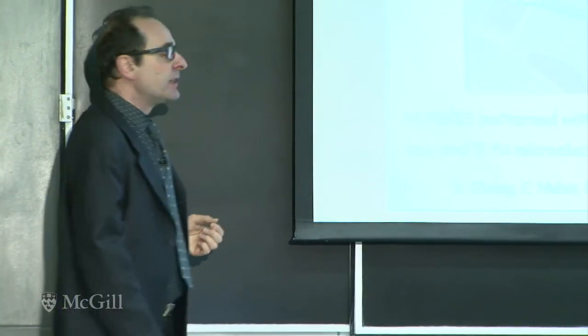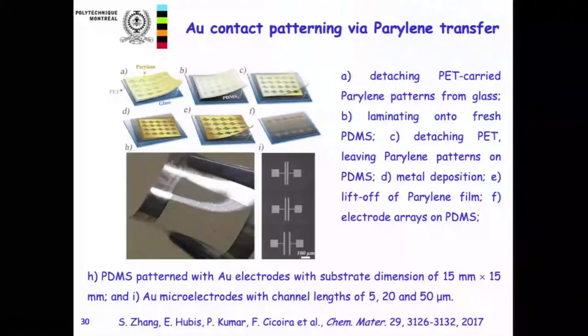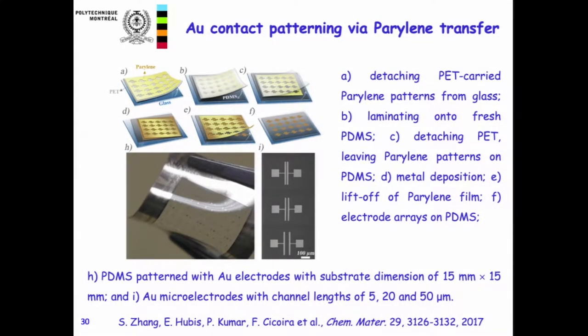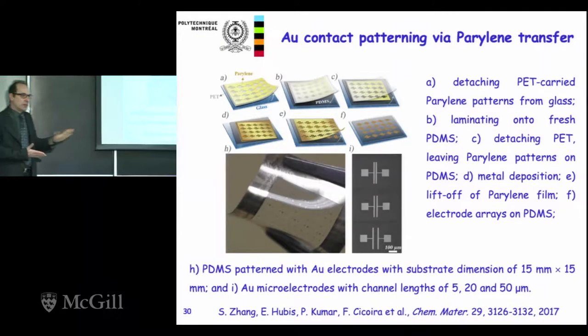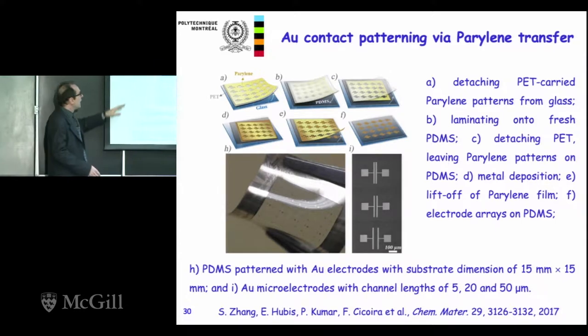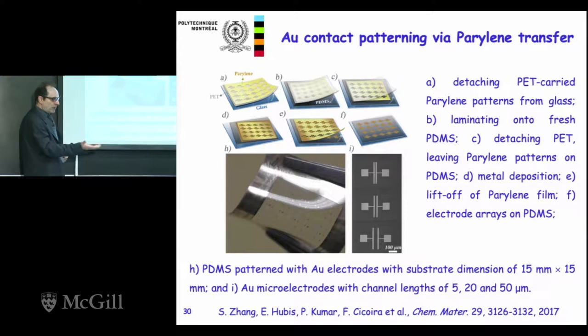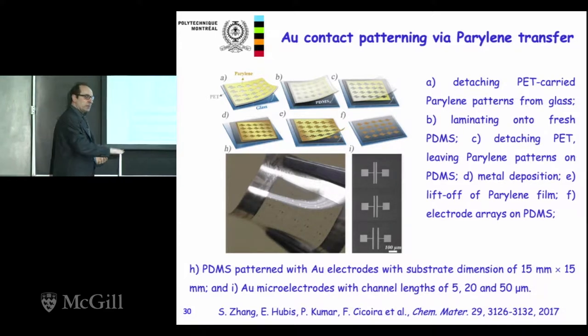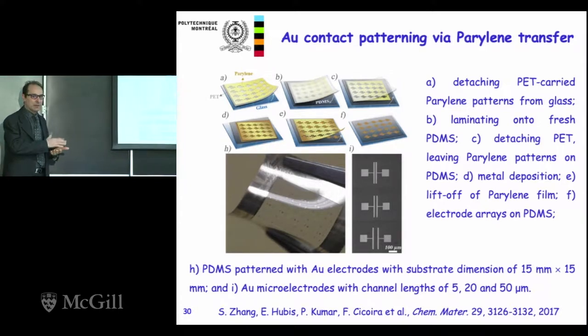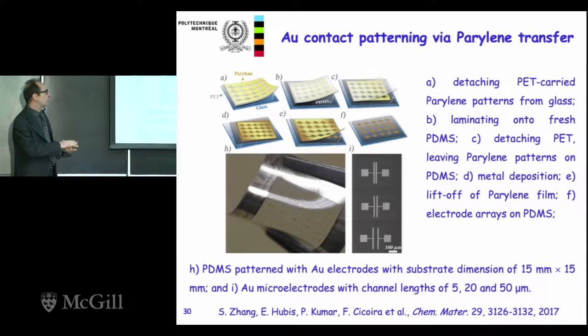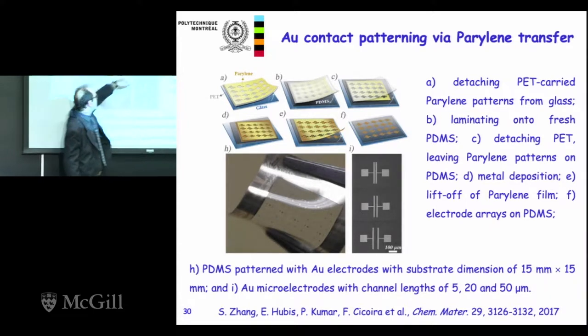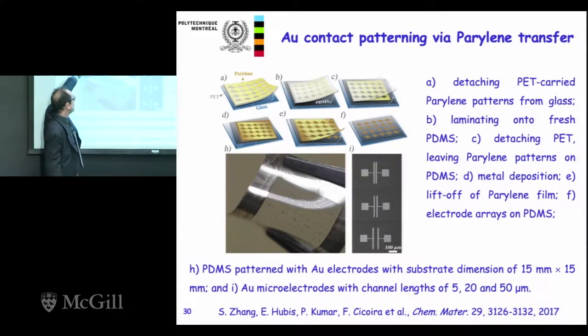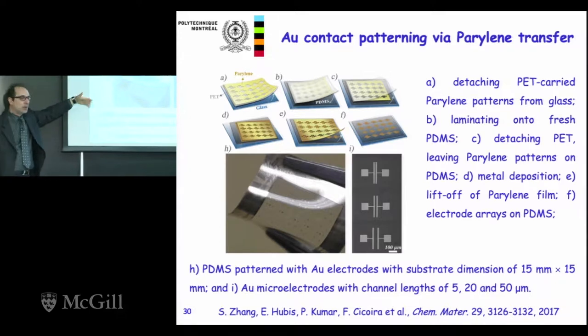Then, of course, a few words about the processing. So first of all, it's not trivial to metallize PDMS. It's actually very challenging, even with lithography. And then we had to find a kind of new process to make this. The way we did it, we used transfer patterning. So we started with a PET sheet on which we deposited the parylene layer. Parylene is a very thin polymer layer that can be patterned by conventional lithography. We patterned the parylene by conventional lithography. And then we transferred the pattern from the PET to PDMS just by sticking the PET on the PDMS. PDMS is much stickier than PET, so the patterned parylene layer would transfer to the PDMS just by contact. Then we remove the PET, and we have this patterned parylene, which acts as a mask, for instance, if we evaporate gold contacts.